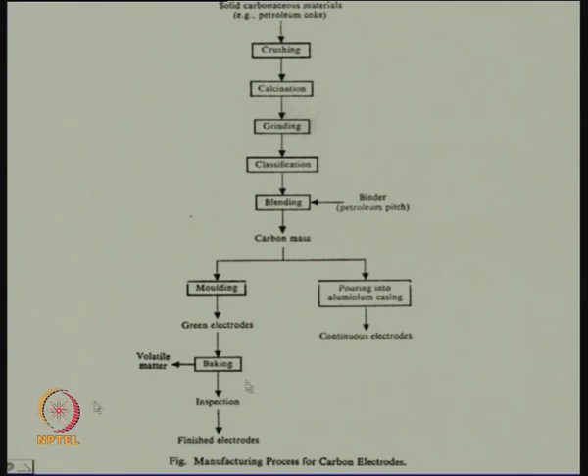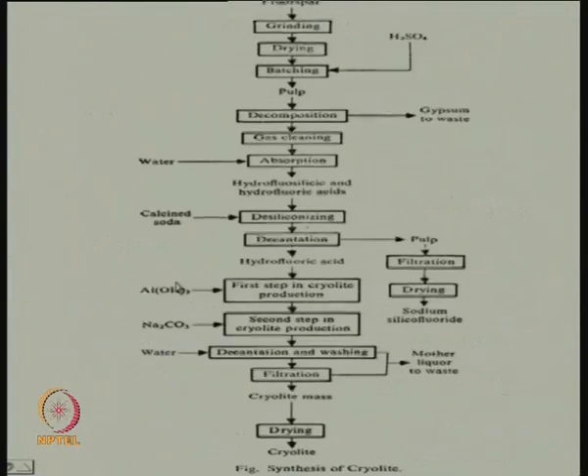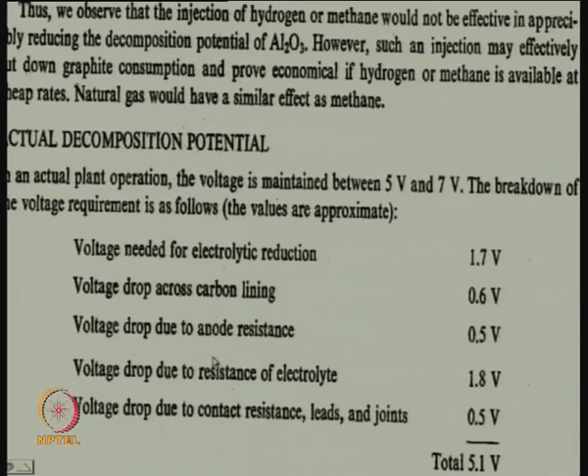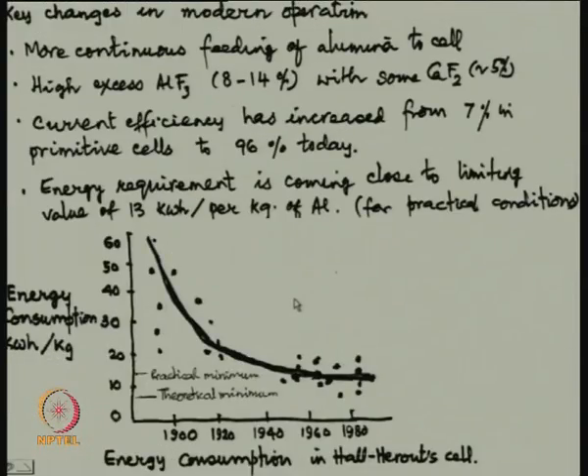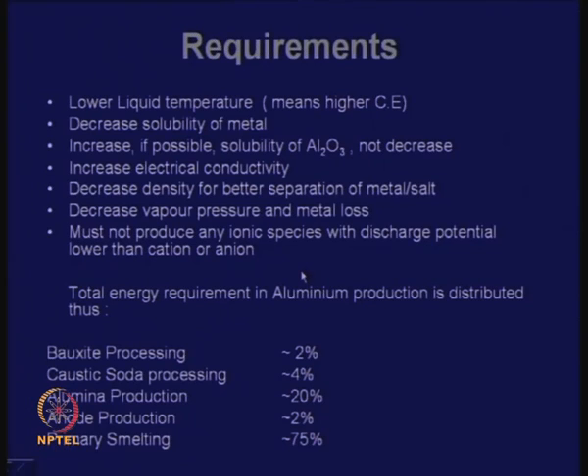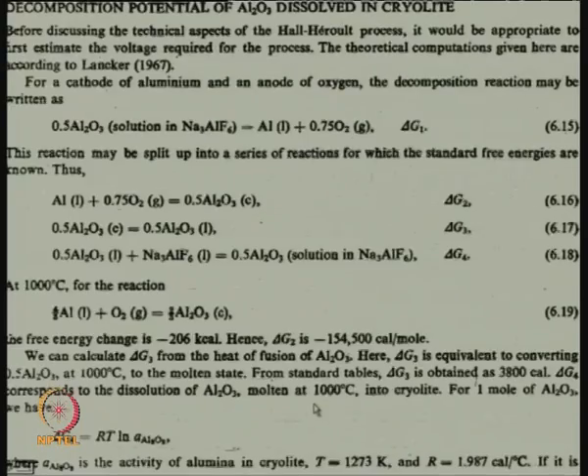Or in Soderberg, the electrode is a paste which is straight away poured into an aluminum casing and is continuously fed into the cell, and it gets dried up as it goes lower down, so that by the time the bottom comes in touch with the electrolyte, it has been baked. But look at all the elaborate processing that is required. You have to start with petroleum. So, it is not only an expensive raw material, it is also an energy consuming thing. You would have seen I have given you some data that the whole process consumes some energy. Somewhere I gave how much it will be required. Here, anode production, 2% of the energy of aluminum electrolysis is involved in that anode production because of all those problems.